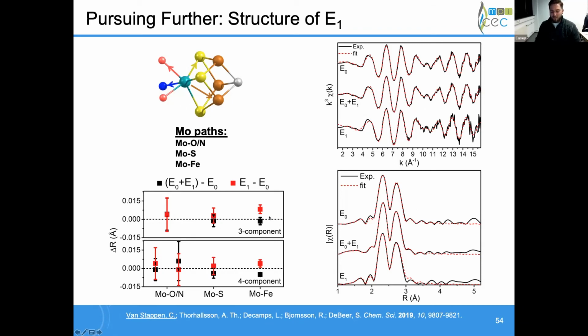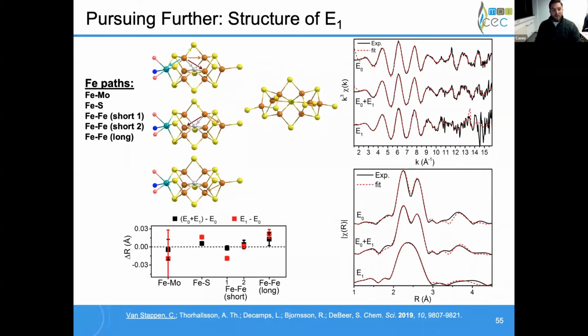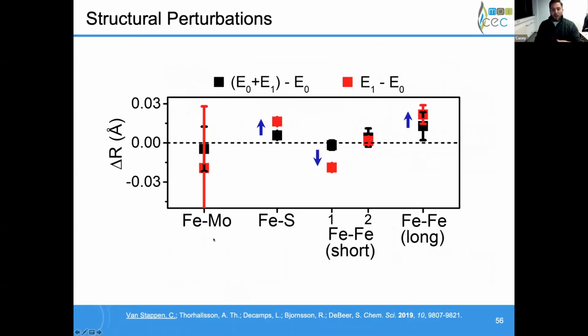and it supports that really we don't have any effective change in distance. From the iron side, as I talked about before, we also have our iron-molybdenum path that we've added into this, but we do have significant distances, and those do trend a little bit. And importantly, our iron-sulfur distance seems like it increases. Our short iron-iron distance, which is this mixture of FeMoco and P cluster, changes a little bit, and so does our long iron-iron. And just as a reminder, the long iron-iron is a really good indicator of what's going on for FeMoco,